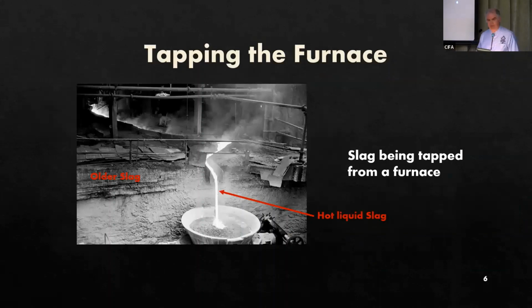So in tapping the furnace, when a furnace is tapped, the slag is removed first because the slag is less dense than the iron that is more dense underneath. So in the early furnaces, the slag was directed to gutters and then allowed to flow out onto the sand in the casting room where it cooled.